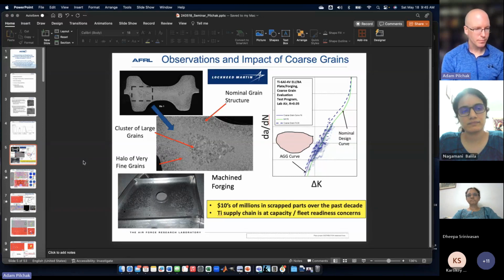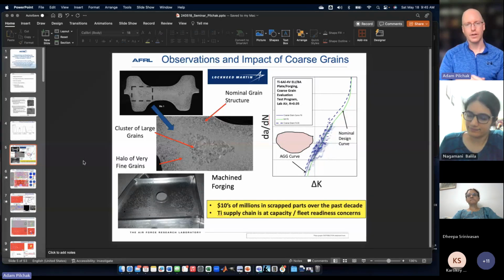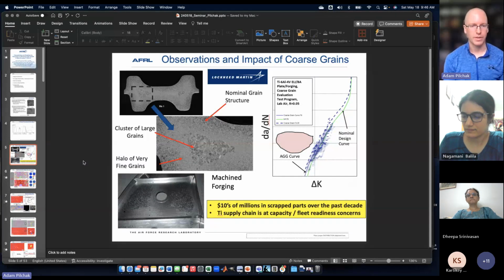So it's good practice to do a couple of experiments to certain surface crack lengths, then stop the test. You can heat tint the material to make it a different color and break it open, so you have a clear witness mark of what the aspect ratio was at a couple of different crack length increments.